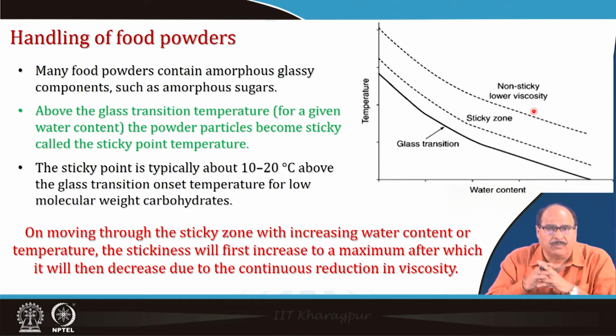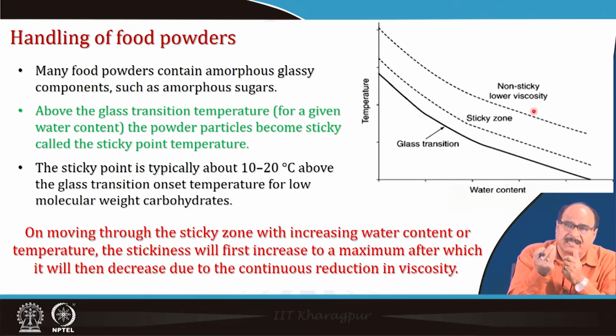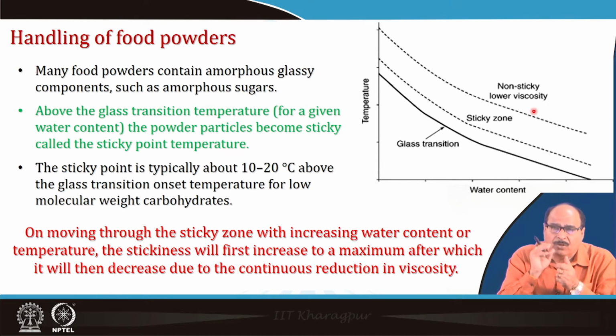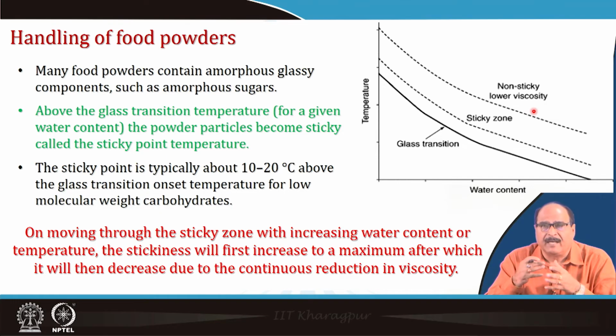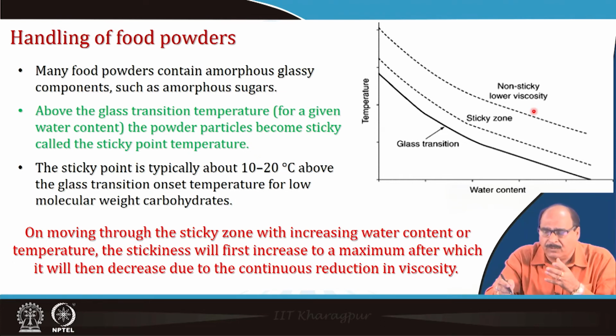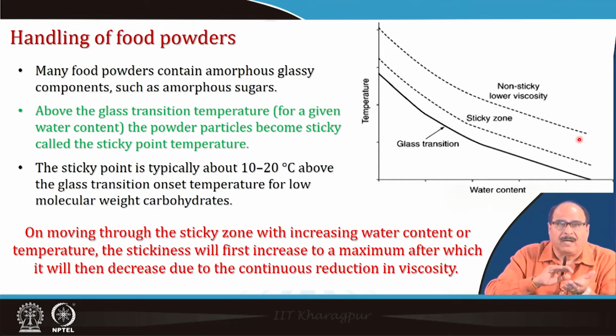Then comes, finally, handling of food powders. Many food powders contain amorphous glassy components such as amorphous sugars, particularly in the case of fruit and vegetable powders. So they contain monosaccharides, and they have low melting properties, low glass transition temperature, and therefore they are very hygroscopic. Above the glass transition temperature for a given water content, as you can see in this figure, this is the glass transition line, above that is the sticky zone, and then finally comes the non-sticky or lower viscosity zone. If above the glass transition temperature, the powder particles become sticky, and that is called the sticky point temperature.